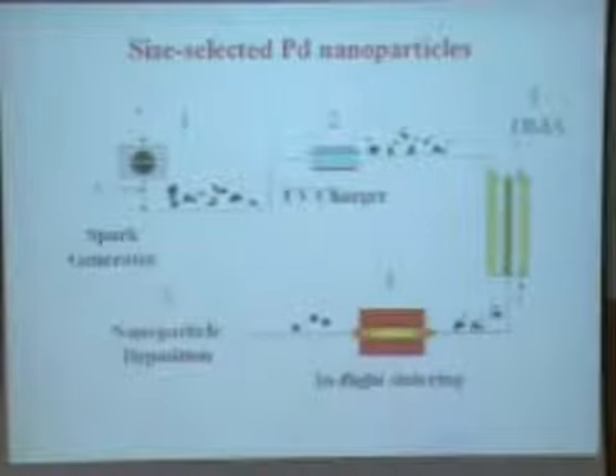As the palladium atoms go into the vapor phase, the inert gas, nitrogen, carries these atoms along this pipeline. As the atoms move in the inert gas, they collide with each other and form different types of agglomerates. These agglomerates have different sizes and different shapes. This is what you normally deposit. When people make these nanocrystalline layers, the layer can have agglomerates of different shapes and different sizes, with no control on the size. You can change the average size of these agglomerates by changing the flow conditions, but there is always going to be a very broad distribution. I will show you the distribution at this stage.